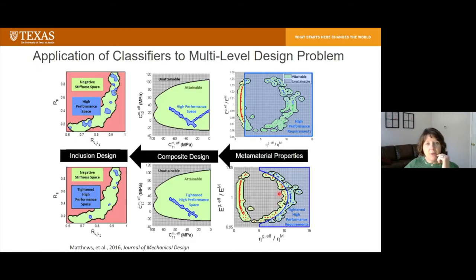So here's what it looks like when we apply it to our design space. What we can do is highlight certain areas of the space, as we did in blue here in the upper right. We can map that back to good properties of our inclusions. So these are effective stiffness properties. And then we can map that back to good design variables. So these are essentially different geometric parameters that define the design of the inclusion. We can tighten that space and see the blue design spaces tighten up even more.